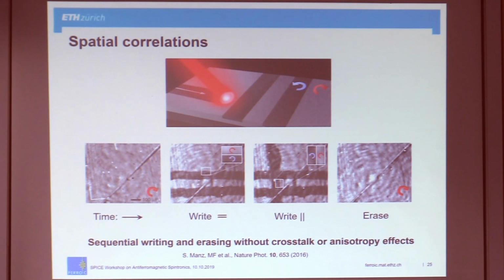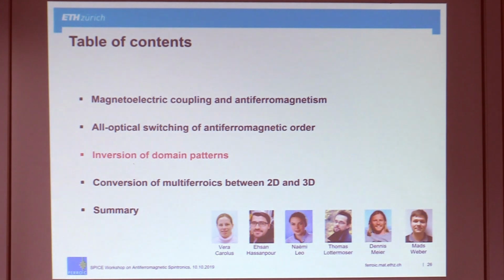So if we write certain structures into our sample, especially if we write cross lines, then you see that there's no crosstalk. So it could happen that in this corner here, the material sees the environment has already switched, so maybe it switches as well. But no, you only really switch where the laser beam has hit. There's no crosstalk. That is quite interesting or quite nice for any type of application you may come up with, of course, at higher temperature in other compounds. You can also erase the entire structure with the other light wave.